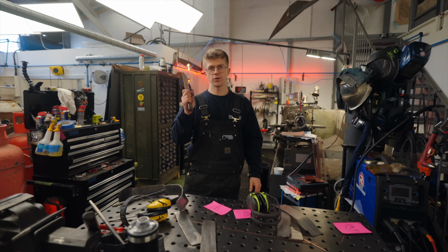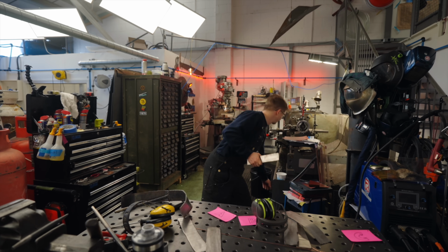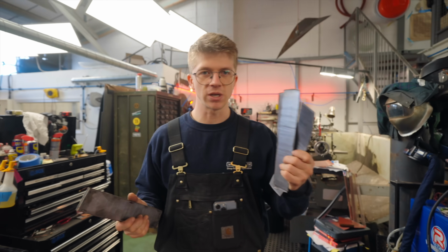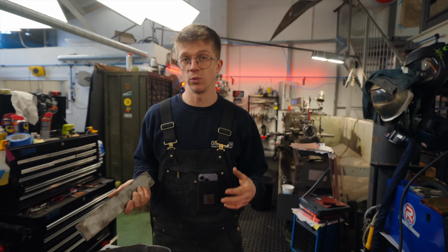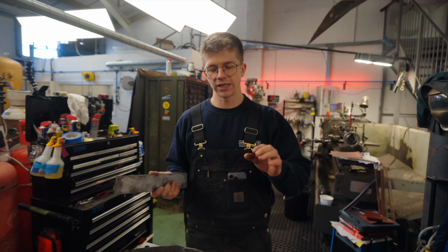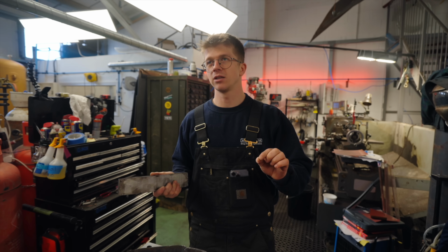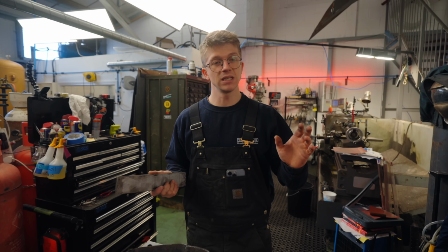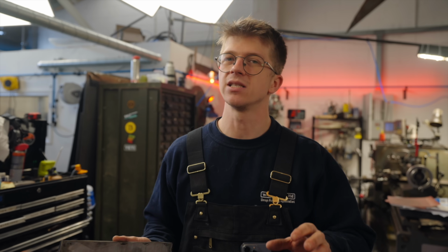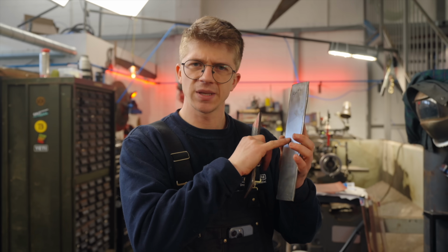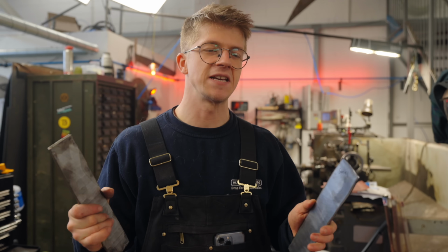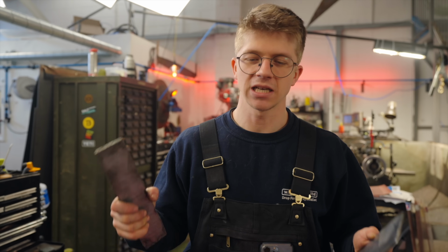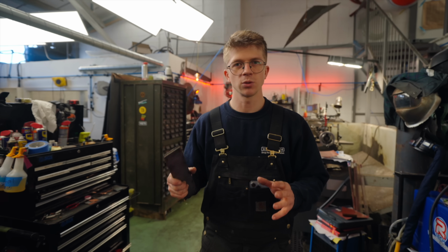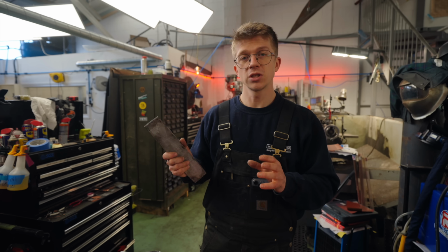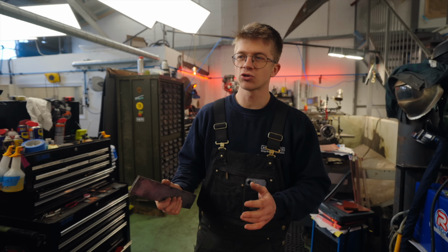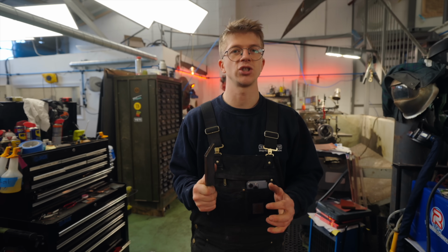So, we've got something that we can try and make a knife from, which is beautiful. But I've got some ridiculously large question marks about the actual bonding process that we thought was pretty well dialed. I don't think it is quite so well dialed. I think that some of the things that we need to try the next time we do it are making sure that the bonding pressure is much higher, as being able to see some of the surface finishes in the bonding interfaces tells me we have not smished it close enough to that atomic contact that we require for a proper diffusion bond. Because the pressure during bonding is something we can control, I think it's something that we should try and change on the next set.